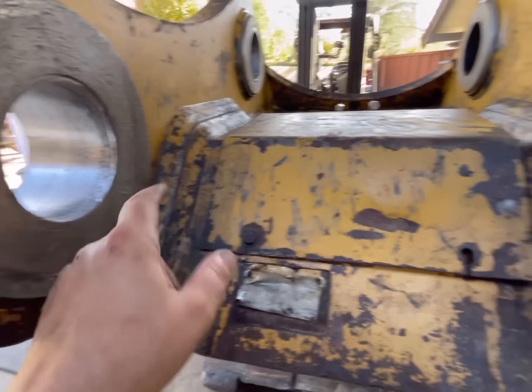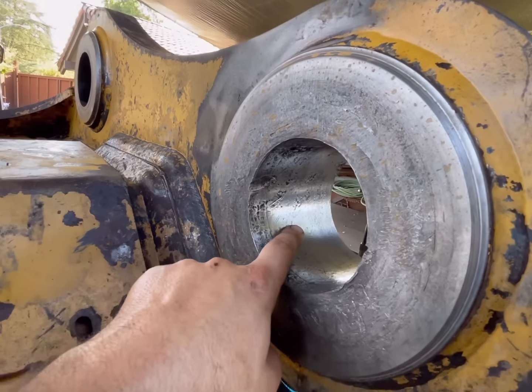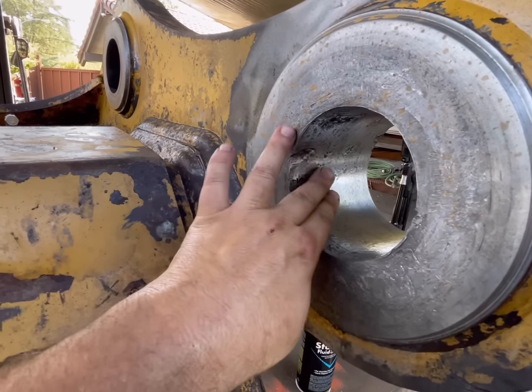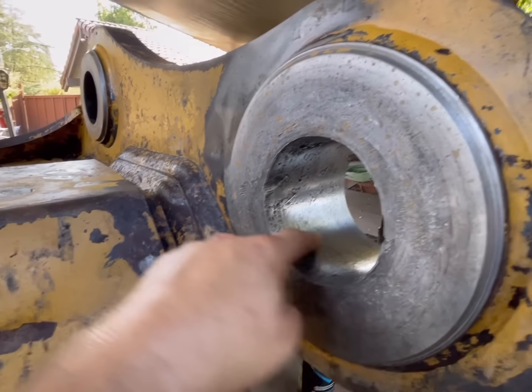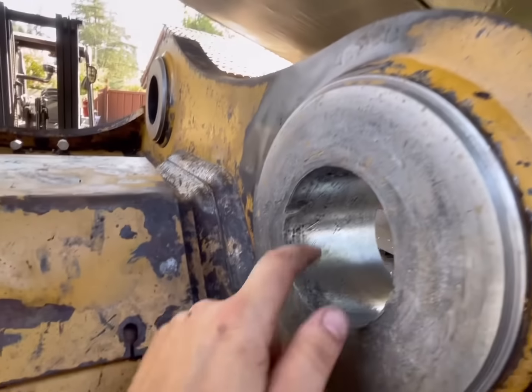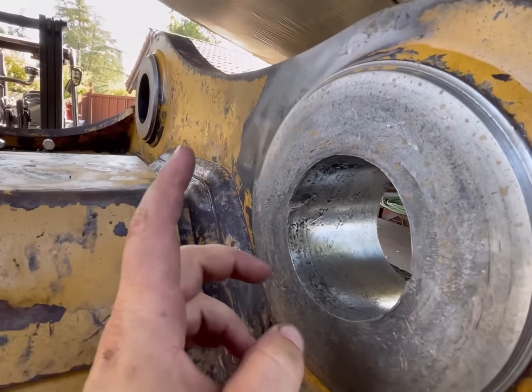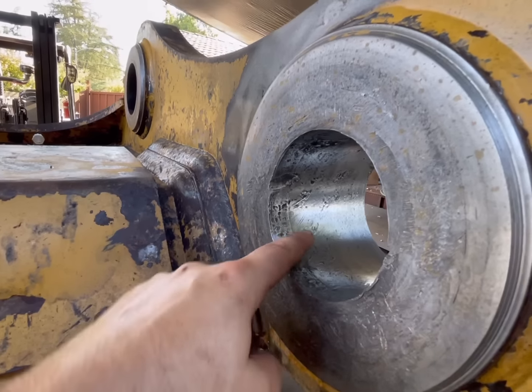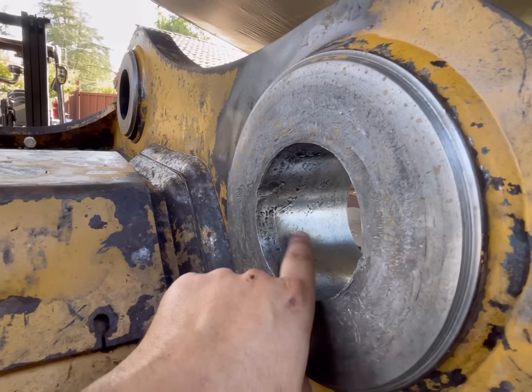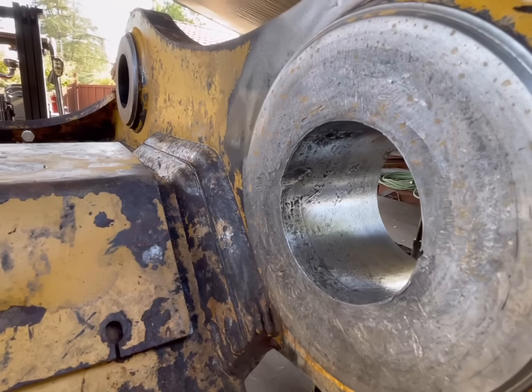those pieces of bushing. So when we go to weld this, if there's any of that bushing material in there and the weld goes over that and it melts all that together, that's going to create an extremely hard section in your weld, and it will most likely break your carbide inserts. So basically just cut this out until it's nice and smooth, and you should be able to see a piece of that stuck in there when you're cutting. It should come out, or there'd be a different color and material or whatever.